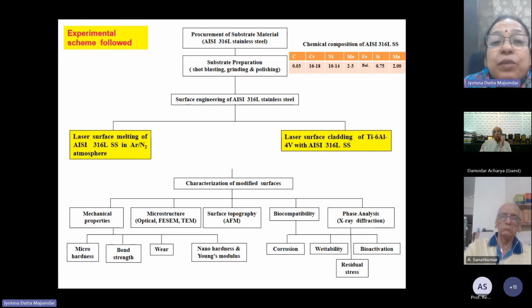Whenever you irradiate a laser beam on the surface, there is the problem of reflection. For the diode laser, we saw that around 80 to 85% of the light is reflected. So we prepared the samples by sandblasting, and then did laser surface melting using argon and also nitrogen as the shrouding environment, and we did all kinds of characterization and testing.